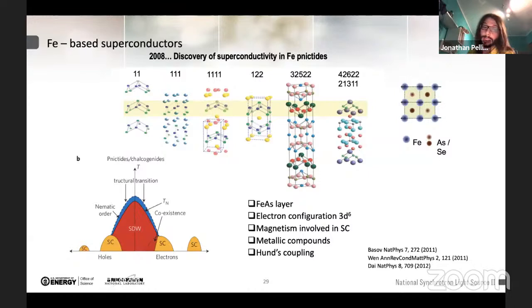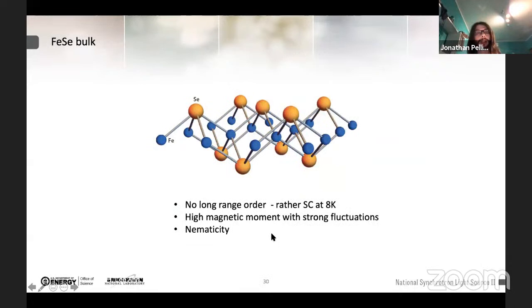Differently from the cuprates, however, these compounds are metallic and they are also multi-orbital systems where the electronic correlation also arises from Hund's coupling. Now, in more detail, I want to focus on iron selenide, which is a pretty special case within the iron-based superconductors because it has a simple structure. In fact, it is composed only of an iron layer with selenide ions above and below, where iron is tetrahedrally coordinated.